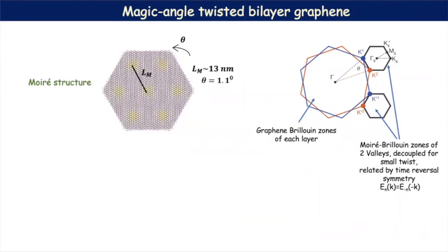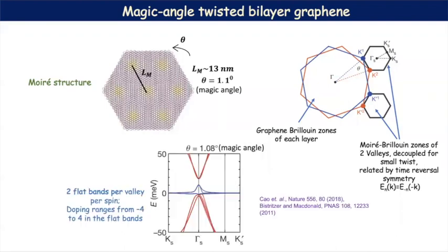So since we already have a nice introduction about these things, I will just quickly get through them. So we have a graphene bilayer with a slight relative rotation. And then we have these large Moiré unit cells. And in k-space, we have small Brillouin zones, and we have 2 copies of it from the 2 valleys of the graphene layers. And at around 1 degree of rotation, we have these flat bands at zero energy. And because of these flat bands, we immediately have an increased effect of interaction in the system. And we see a lot of interesting correlated phases emerging near this magic angle twist.